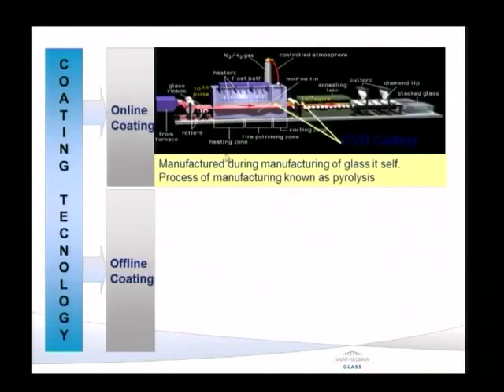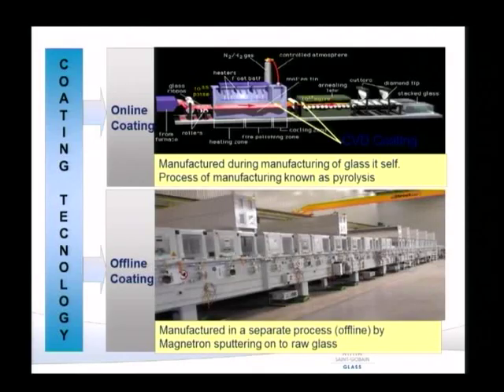Now in the online coating, the coating is done as the glass is manufactured. So as the glass is leaving the float bath, a coating is done at 600 degrees over the glass by passing a gas over the glass. So this, through the process of pyrolysis, forms a coating on the glass. The newer process is the magnetron process, where the glass is sputter coated in a separate chamber. Let me explain this process on the board.